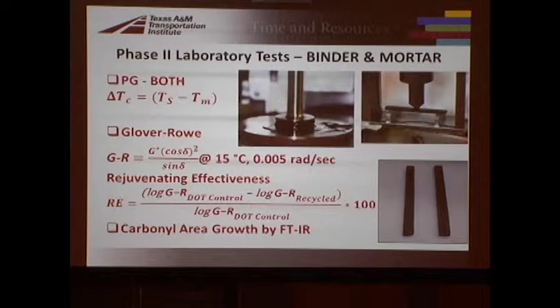Some of the tests that we're utilizing in phase 2: we're doing quite a bit of binder testing. Then we're doing a little bit of mortar testing, which is a way to not have to extract and recover the binder out of the RAP and the RAS, so you're getting a more realistic blend of materials. For both the binder and the mortar testing, we're doing the PG grading using the DSR and the BBR like we normally would.